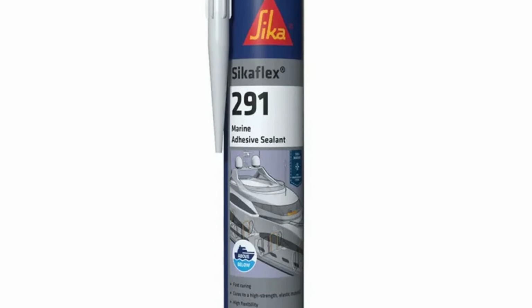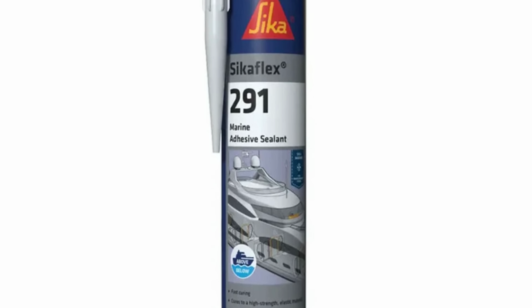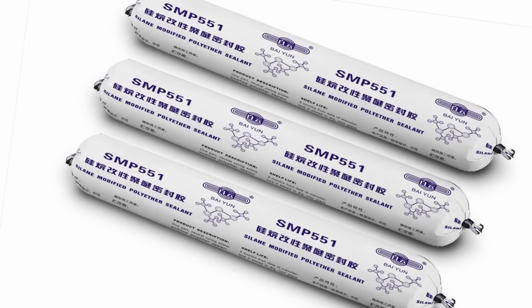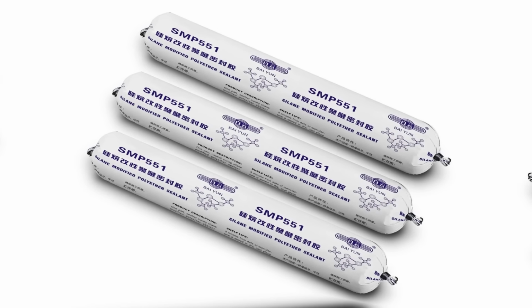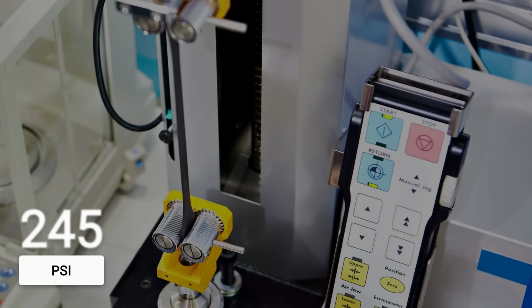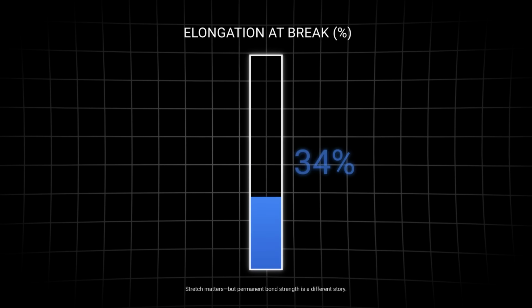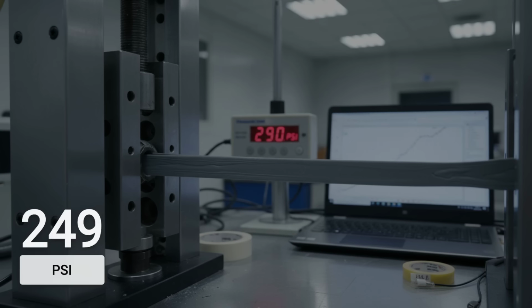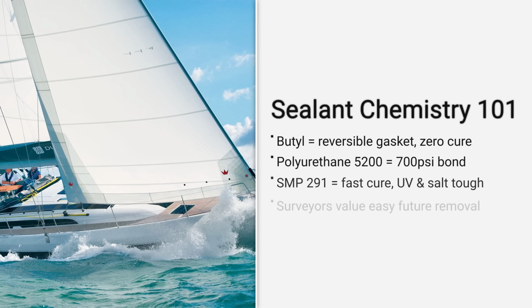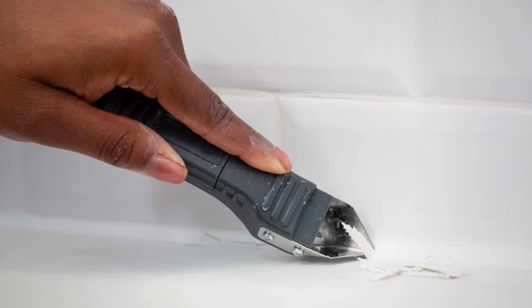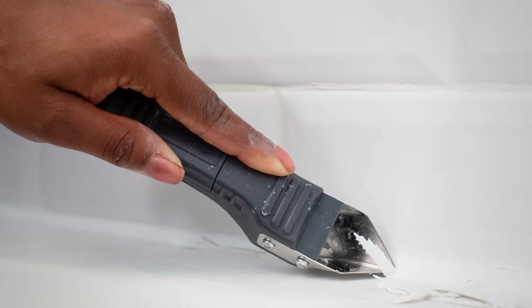Sikaflex 291 and polyether SMPs, Loctite, Sabatac, and Mastersil offer a different balance. Still moisture curing, they trade some strength for flexibility. Sikaflex 291 clocks in around 260 pounds per square inch tensile, with elongation up to 500%. Mastersil, an SMP, reaches about 290 pounds per square inch. These adhesives flex with the boat, cure faster than polyurethanes, and handle ultraviolet and salt better, but once cured, they are still a permanent bond.